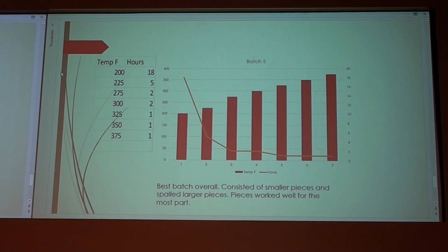This is less sensitive than Knife River Flint. Knife River Flint is pretty sensitive to heating up and down, so in contrast to this, you have to make sure you do the cool down cycle, and do it for about as long as you do the heat up cycle. So batch 5 seemed to be doing what I wanted it to.